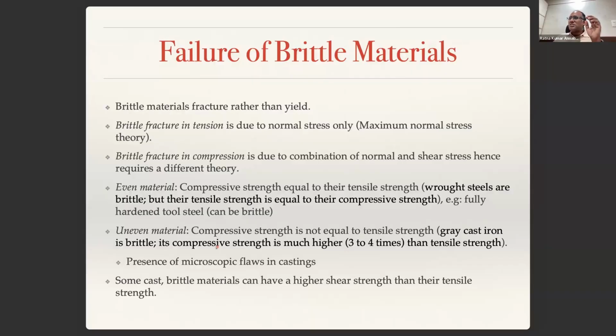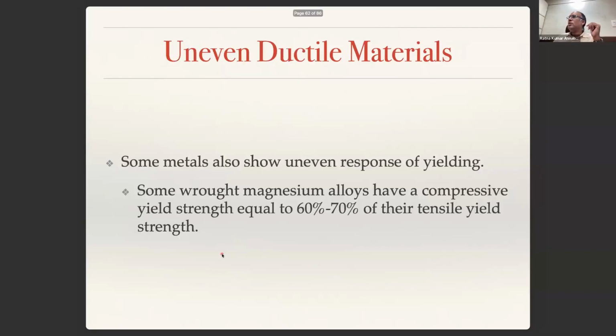This is because in castings, you have several microscopic flaws and they lead to fracture. So it's much easier to break open a crack under tension rather than under compression. That is why under compression, they will have much higher strength. Sometimes some metals also show uneven response in yielding, but let us not worry about that at this point of time.